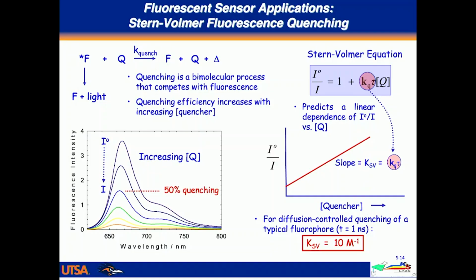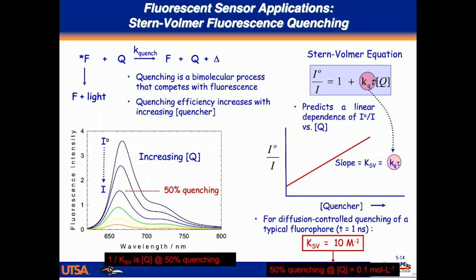Okay? In most simple molecular systems where you add a molecule as a quencher, you get a nice straight line. Typically, if it's a small molecule and a fluorescent molecule with a lifetime in the range of a few nanoseconds, you'll get a typical slope in the range of around 10 per molar. Now that probably doesn't mean much to you right now, but just pay attention to the units. That's inverse molar, so this is 1 over concentration. And what does that Stern-Volmer constant really mean? Well, if we take the inverse of that number, 1 over 10, that corresponds to the amount of quencher that you need to add to get 50% quenching.